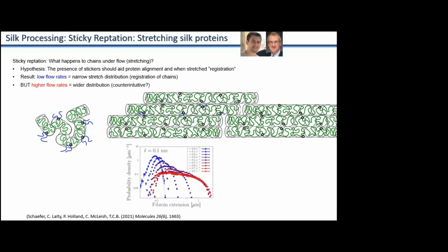But at higher flow rates, unfortunately, we start to see this wider distribution of stretch, which kind of doesn't make sense. We want everything to be nice and even. At sufficiently high rates, we observe that the stretch distribution converges to a steady distribution independent of flow rate, and sticky chemistry is the main control parameter.